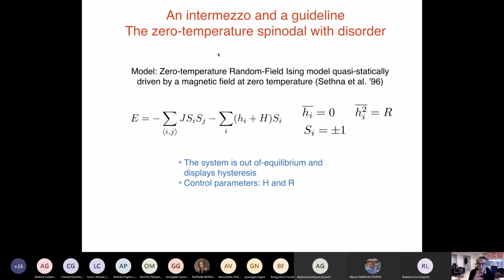It's important to have disorder, because in amorphous solids, clearly there is disorder. And we know that this is an important element. And so what we are going to study now, and what I want to recall to you, because it's also an interesting problem per se, is the physics of the spinodal of the random field Ising model at 0 temperature. So we're going to take the random field Ising model, let's say with all the spins which are minus, for example, and then we are going to change the magnetic field very, very slowly. Each time the system will just go to the minimum energy, and we are going to follow what happens to the configuration, in particular to the magnetization.